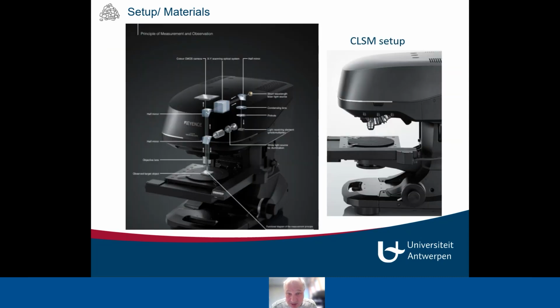Our confocal microscope contains two techniques. There is an optical confocal microscope in it, and there is a laser. So we can use both techniques in this machine. We can have an optical confocal image, and we can go up to almost 24,000 times magnification. And we can make a 3D scan of the specimen with a laser. So that's a very advanced machine. And this is really contactless, so you don't have contact with the sample.